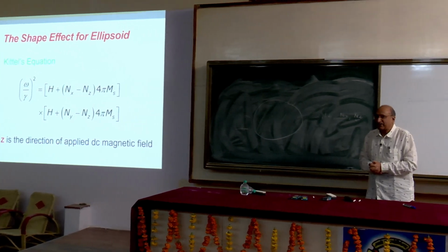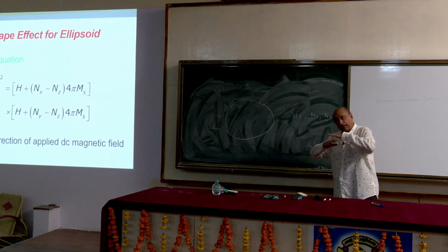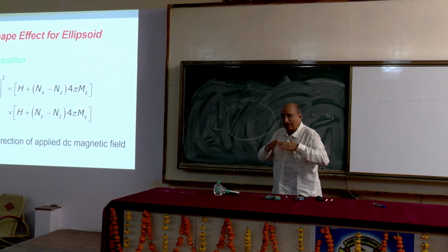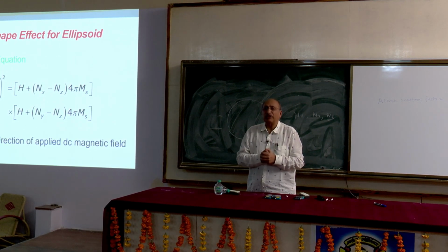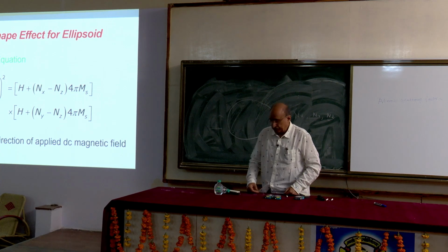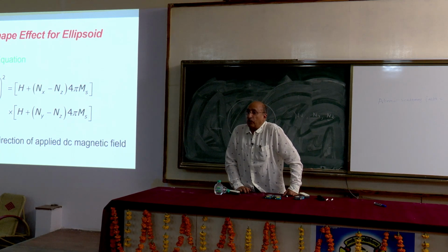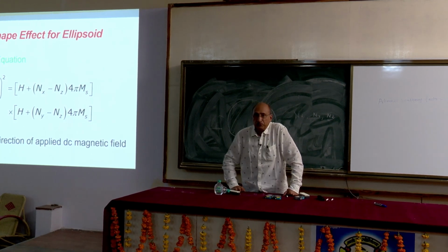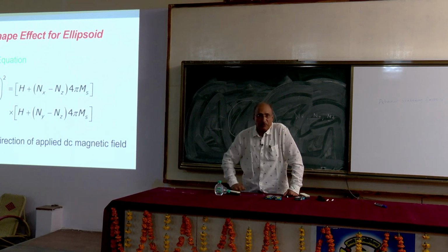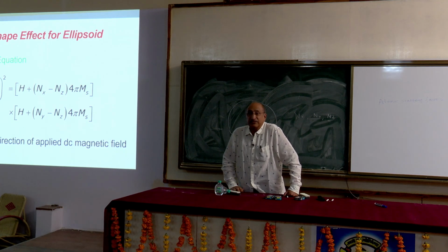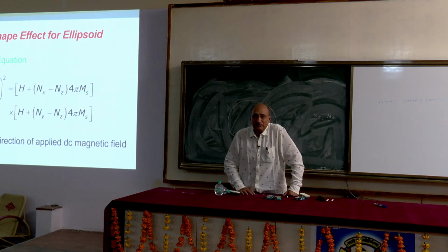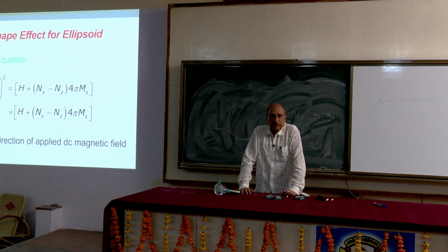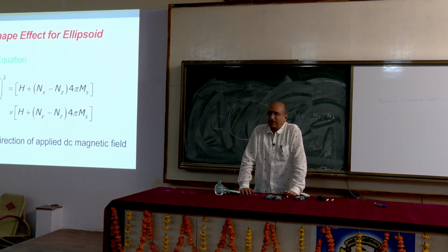I would like to have a better sputtering unit or better ablation where I deposit much better films, and we will work and try to get it. But on the other hand, normally it will not happen perfectly. Now, if somebody asks you to calculate 4 pi Ms from your VSM data, I must know the volume. For volume, I must know the thickness of the sample. And because thickness has its own inherent uncertainties, 4 pi Ms will have a certain amount of error. While here you are getting it directly. That's one of the biggest advantages of a resonance experiment.